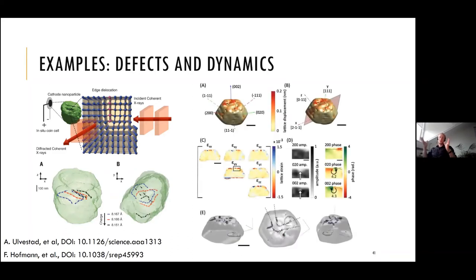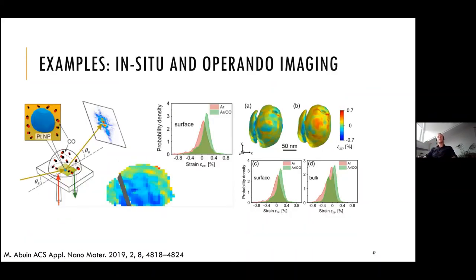Or you can study the full three-dimensional tensor of simple objects, but under very harsh and extreme conditions, like ion irradiation happening in a nuclear reactor, for example. You can also go into in situ and operando imaging, which is a highlight of the technique, where you can combine this simple Bragg CDI measurement with advanced sample environments and get access to the structure while some processes are happening. This example is the surface oxidation during the catalytic reaction of platinum particles inside a dome. So all kinds of combinations can be done, and it's very exciting and sometimes, of course, also challenging, but it's still in the development phase and very interesting to work in.